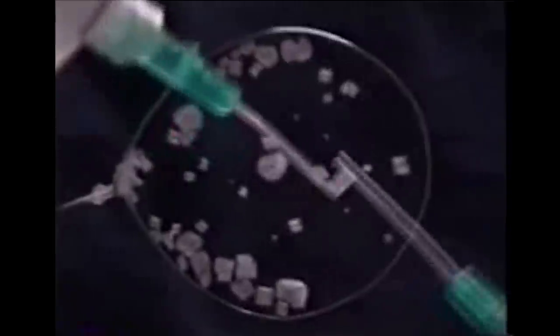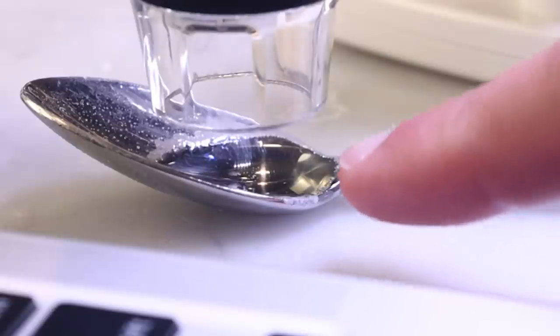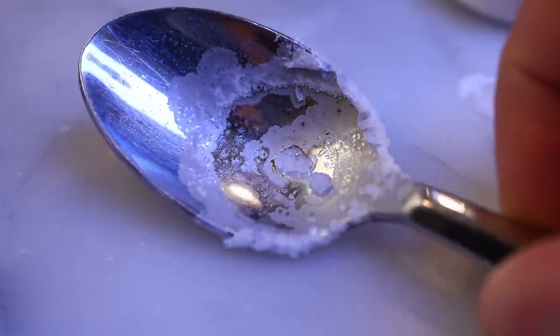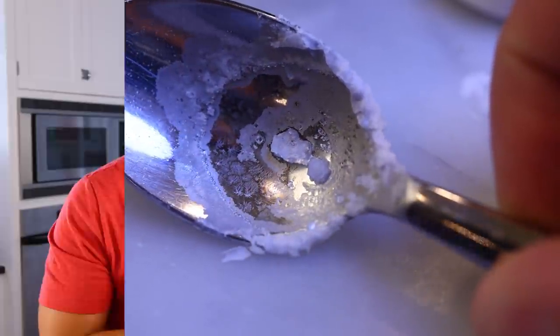Of course, to do that, you'd have to keep isolating the crystals, pull out a good one, and get it growing by itself in a fresh film of brine. This is true on Earth as well. If you let multiple crystals keep growing near each other, they may eventually agglomerate or cake together. That's what happened in my spoon experiment. The crystals bond together in what's called a raft, and thus their growth is restricted. In every attempt that I made to grow big hopper crystals here at home, agglomeration was the main limiting factor.